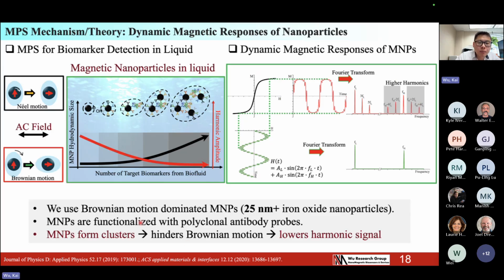Usually we use Brownian motion dominated nanoparticles, which means the signal mainly comes from the Brownian motion of particles. However, if the Brownian motion is blocked, we will see a drop in the harmonic signal amplitude. The drop in the amplitude of harmonics is proportional to the amount or concentration of the analyte in the solution. So the whole logic is that nanoparticles will form clusters in the presence of analyte. This will hinder the Brownian motion, lower the dynamic response of particles to the magnetic fields, and lower the harmonic signal we observe. Okay, so this is the whole story of how the MPS works as a quantitative biosensor platform.